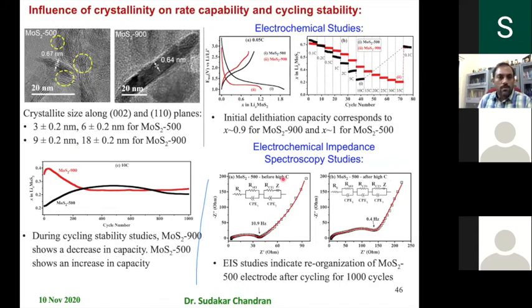In fact, we also studied the extreme cases like 500 and 900, as I discussed in the magnetic properties. One interesting thing we found is when you do the cyclic studies at high C rate, the 500 one initially keeps on increasing, almost up to 500 cycles, it shows an increase in the capacity. Almost it goes from 0.2 to 0.3, and then it slowly decreases. Whereas the 900 one keeps on decreasing. So the structural changes that happen with the cycling mean the lithium is intercalated into the system and then removed from the system, and this is continued, every time checking how much lithium is going in and how much lithium is coming out.